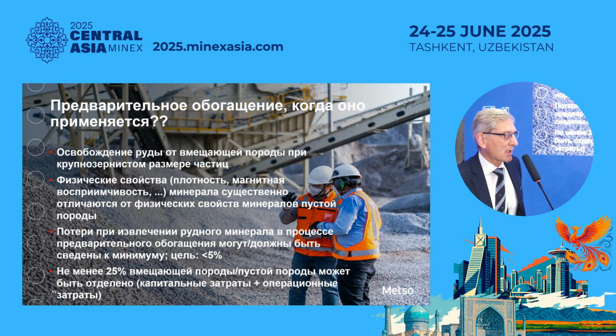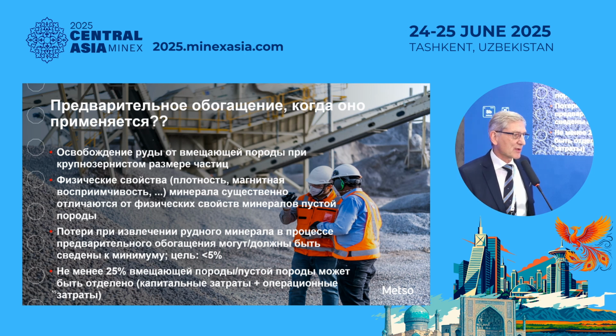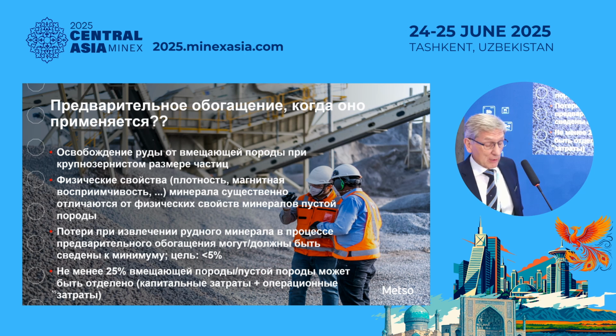Okay, when is it feasible to use pre-concentration? Yeah, when the liberation of the host rock is coarse enough. If the physical properties, density, magnetic susceptibility, of the mineral differ substantially from the physical properties of the gangue minerals. If the recovery losses are minimized, they should be less than 5%. And last but not least, at least 25% of the gangue minerals should be rejected. Otherwise, the capex and the opex are too high for application of this technology.